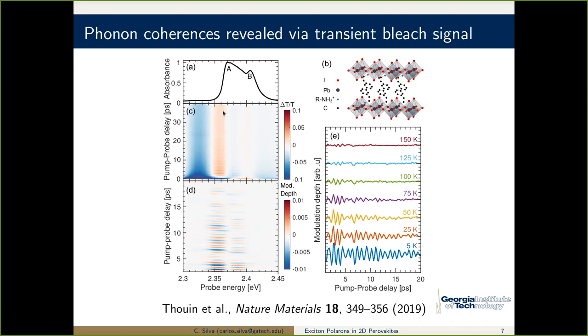Let's not worry about the dynamics or the line shape of the bleach, but let's notice that there's oscillations here, that if we take away the dynamics and just leave the oscillations, we see these wiggles that right at the peak of this main exciton A shift in phase. So we have wiggles up, down, up, down, up, down, that on this side of the maximum of the absorption, it's down, up, down, up, down, up. And so let's just take a projection here.